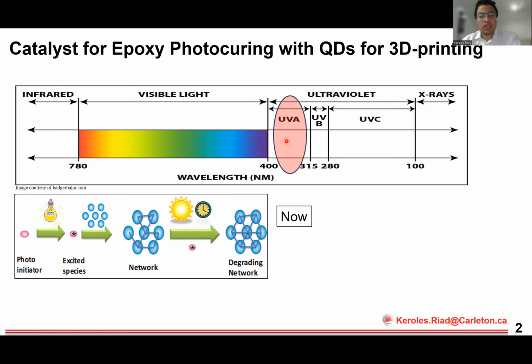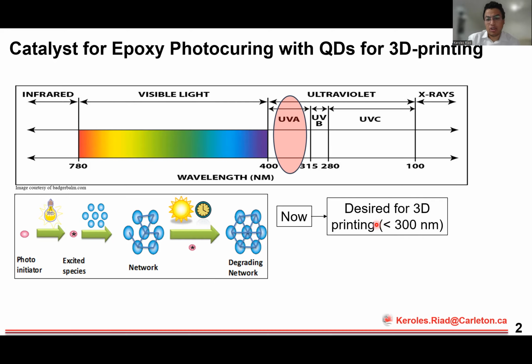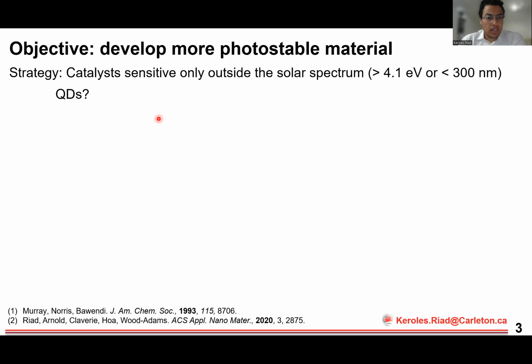And so my goal is to create new catalysts that are sensitive exclusively to light outside of the solar spectrum, which is essentially anything lower than 300 nanometers, which is completely blocked by the ozone layer. And that way I can have catalysts that are sensitive to UVC light, not UVA light, so that I can 3D print with the UV laser, but it will not be sensitive to sunlight. And I would like to do that with quantum dots.